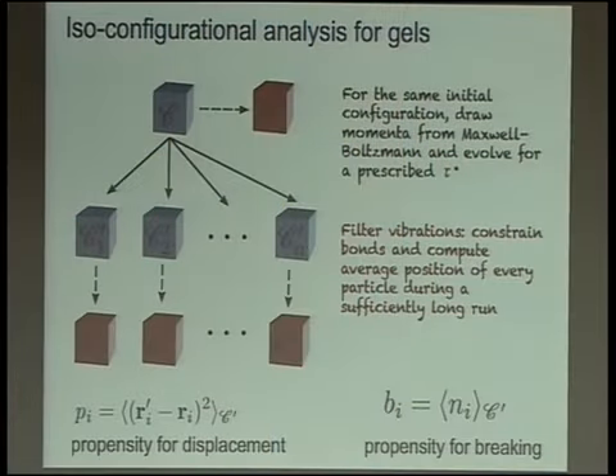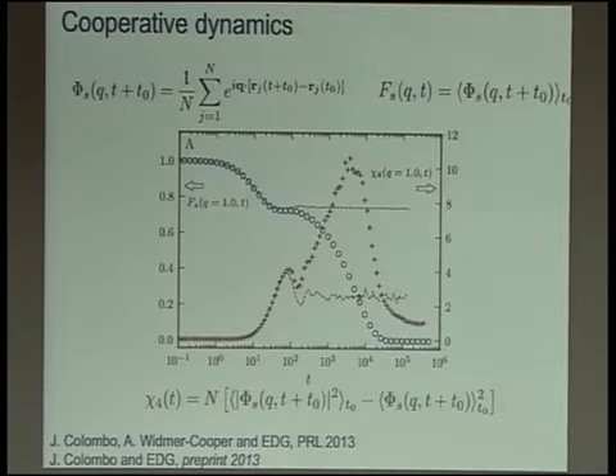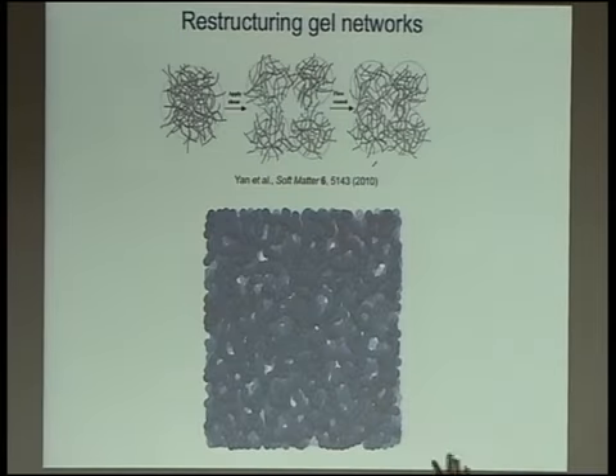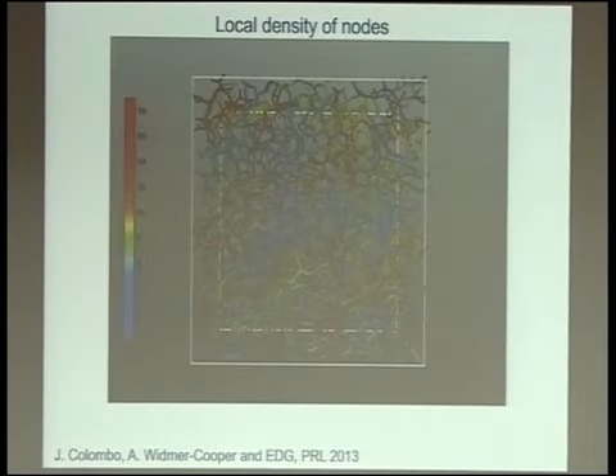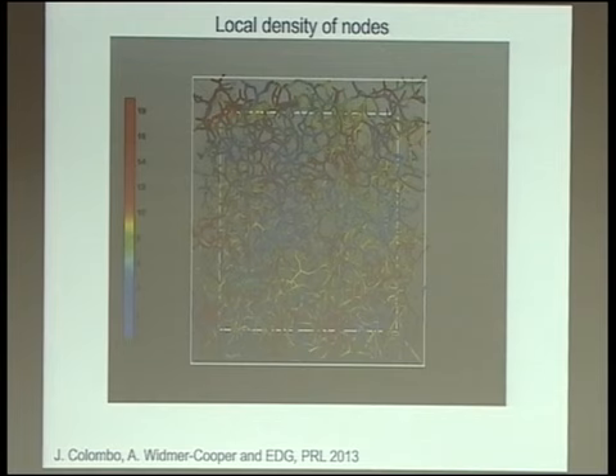So we have a map of displacements that actually correspond to the structural relaxation of the system, the final overall relaxation of the network, and not just the network fluctuations, which have been filtered out. Okay, so what you get is this. No, first of all, let me, so we started from this type of physical picture of the network, and by doing this type of analysis, you transform your physical picture of the network into something like that. So here what we have analyzed is in fact not even dynamical information, but just the local density of nodes in the network.